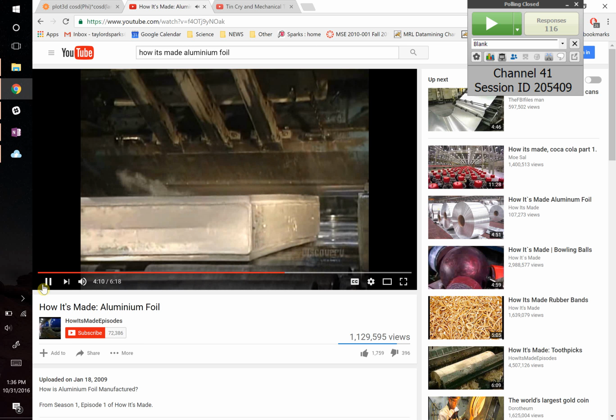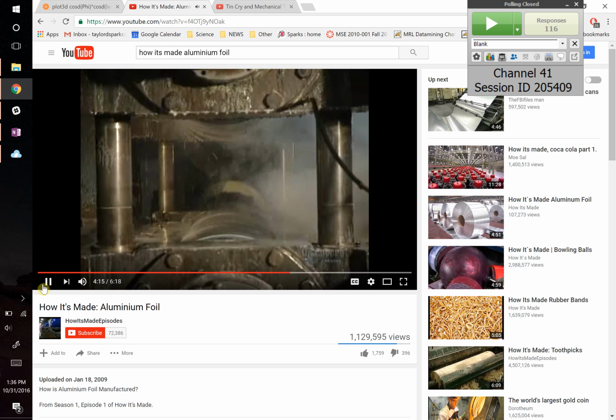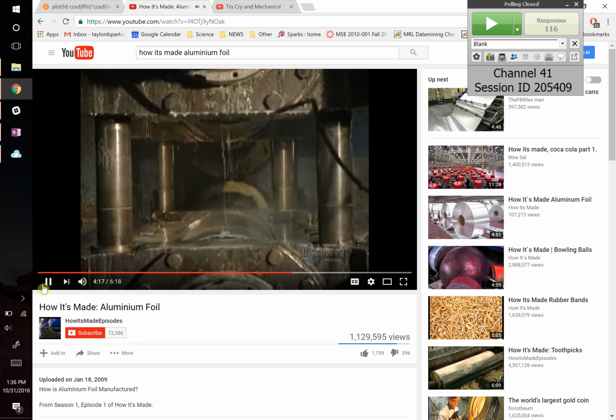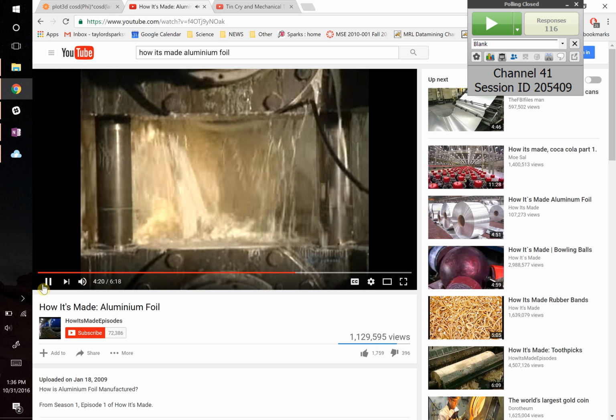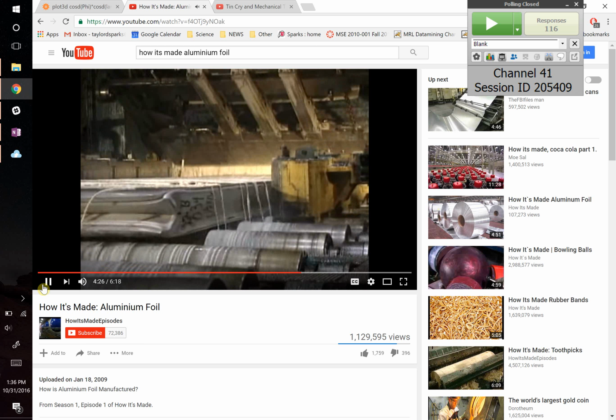They do this at high temperatures so that dislocations can move easier, so you get more deformation for the same pressure applied. To prevent the ingot from sticking to the mill's roller, everything is cooled with a liquid that's 95% water and 5% oil. They have to have that oil so the ingot doesn't stick to the rollers as you're rolling it.